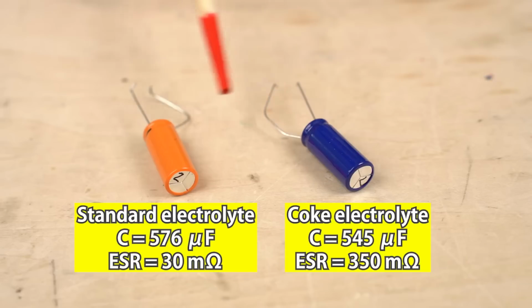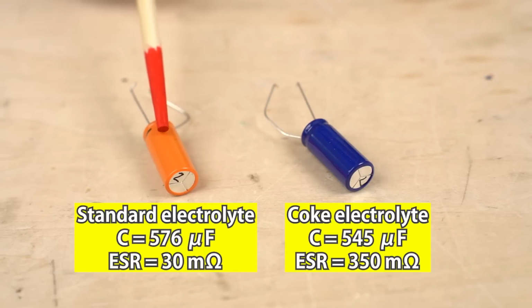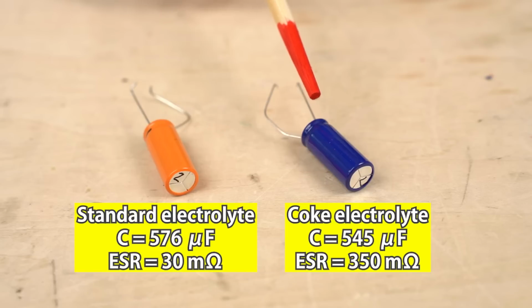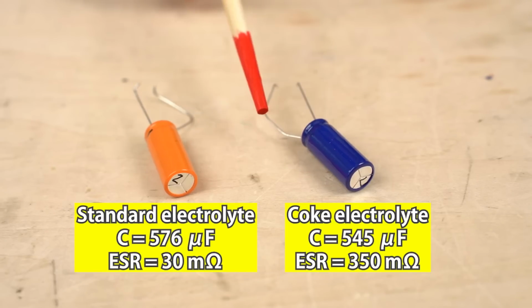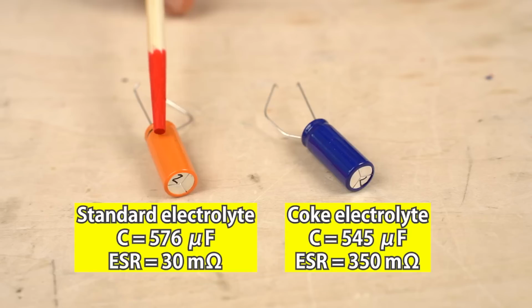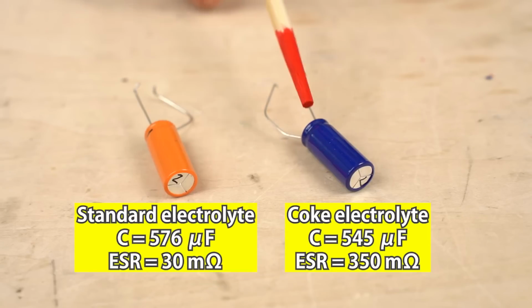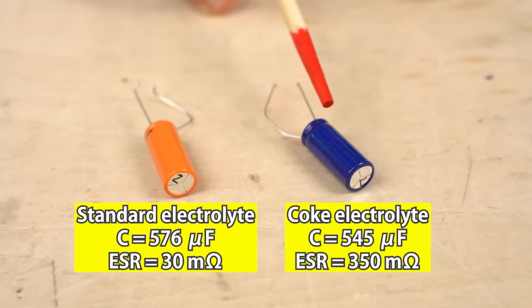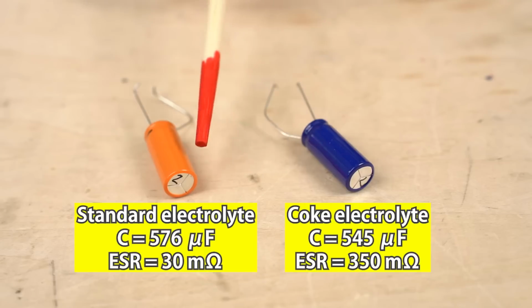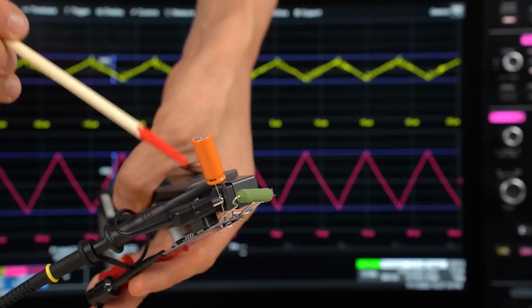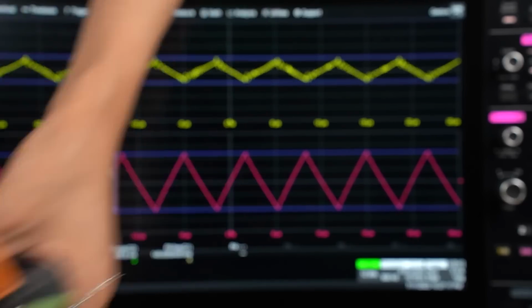The capacitance values are not so different. The standard one is 576 microfarad. The Coke one is 545 microfarad. However, the ESR is significantly different. The standard one is 30 milliohm, and the Coke one is 350 milliohm. Coke one is 10 times higher. Let's see the ripple voltage of these capacitors. Firstly, machine winding capacitor with standard electrolyte.